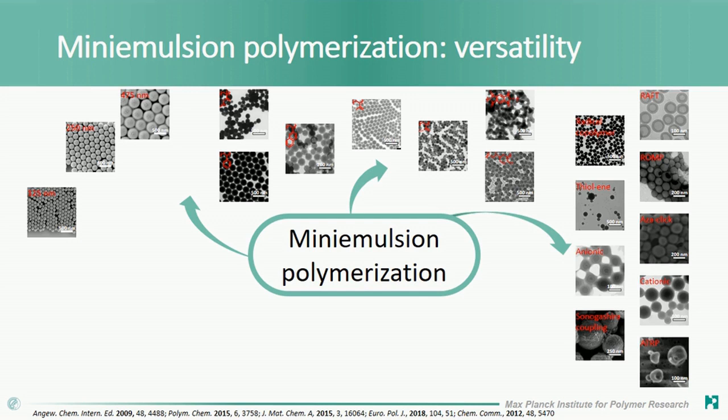With other types of polymerization in dispersed phase, it's really difficult to have well-controlled copolymer structure, because to some extent they are reliant on the diffusion of the monomers through the continuous phase, which leads to gradient in composition or to inhomogeneous composition. While miniemulsion polymerization is probably one of the best ways in dispersed phase to get well-controlled copolymer structure.